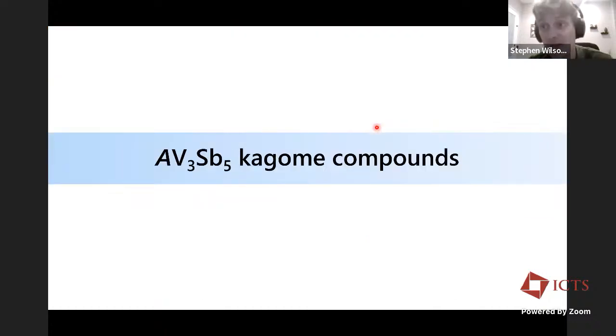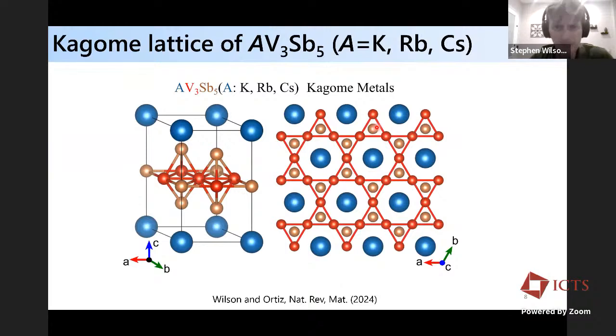Okay, so in the first part I'm going to talk to you about these so-called 135 systems. I think there have been some talks earlier mentioning these systems yesterday. Just as a reminder, the interesting physics arises from the Kagome net of vanadium ions. The vanadium ions are very close together, around 2.7 angstroms apart. So you have delocalization across the Kagome net, and these are paramagnetic systems. The local spin is quenched, and the basic building block is these V3Sb5 blocks, which are then spaced by these alkali layers.